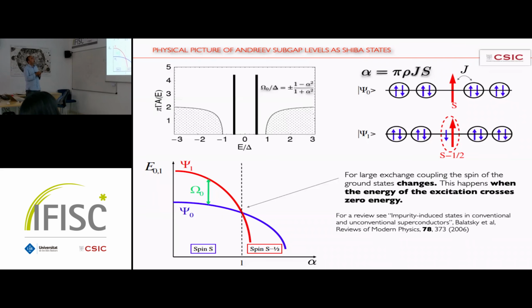And you see here that for alpha very small, near zero, this is essentially 1. So you are right at the gap edge of the superconductor. But as alpha approaches 1, this quantity goes to 0. So the position of this peak goes to 0, all right? Physically, what this means is that I start with a ground state, the standard BCS ground state plus the impurity. The first excitation is going to be this Shiba singlet, and the energy separation between the ground state and this Shiba singlet is given by omega naught, the position in energy of the subgap level. As I increase alpha, eventually this energy goes to 0, as I said.